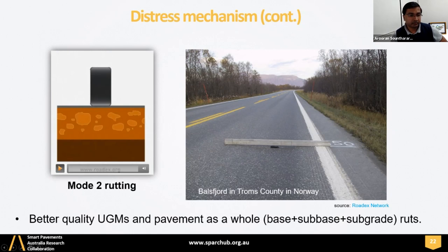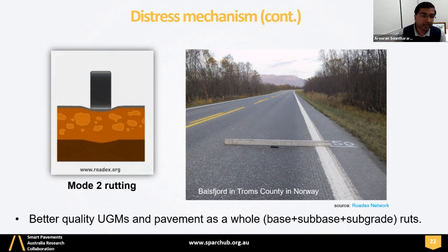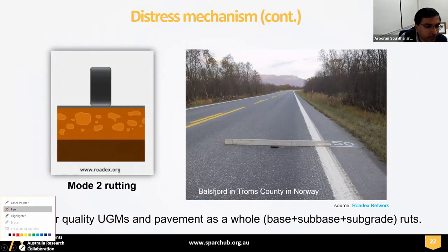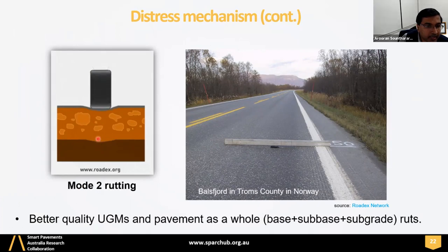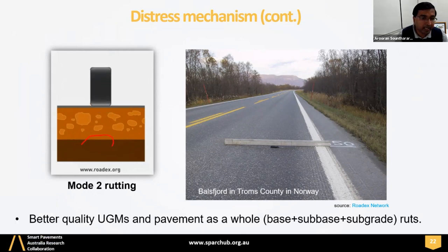And mode two rutting, it's the last type of rutting. This rutting occurs as a whole pavement rut, right? So which means the subgrade, let me take the laser again. So if you look at the rutting profile of the subgrade, the subgrade deforms significantly more than the base. So what happens here is the pavement base is of good quality. Therefore, you see the elastic response of the pavement, whereas the subgrade material is not of good quality. Therefore, you see a significant amount of rutting here.